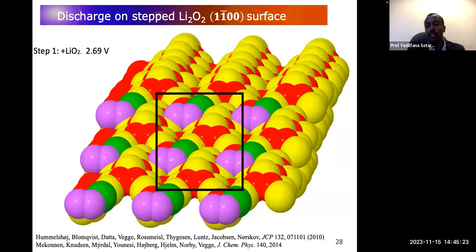And the DFT tells me that the first step is the adsorption of lithium superoxide at the kink site with the energy of 2.69. This is not just found with a single calculation or a one-shot calculation. I tried several sites, several places, and several species as the first step, and finally I identified lithium superoxide at this particular site as the first preferred step with this energy.